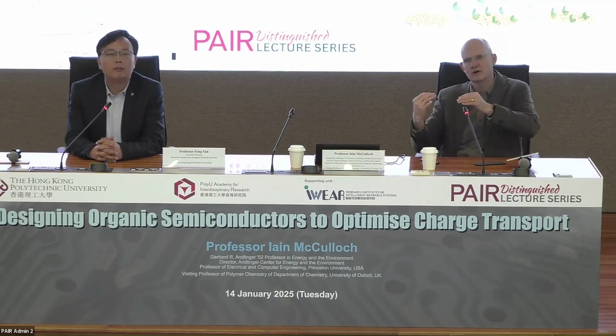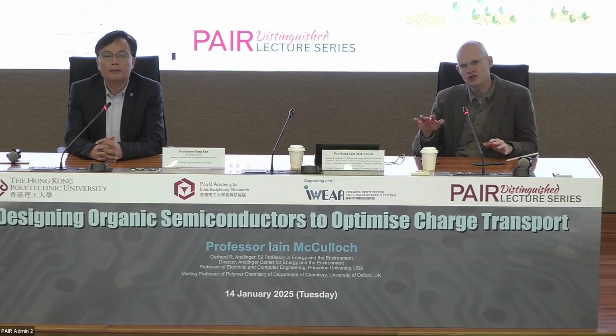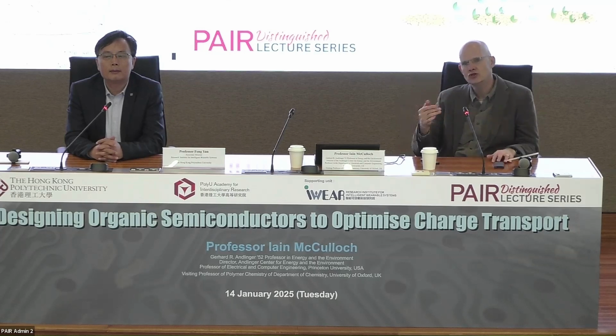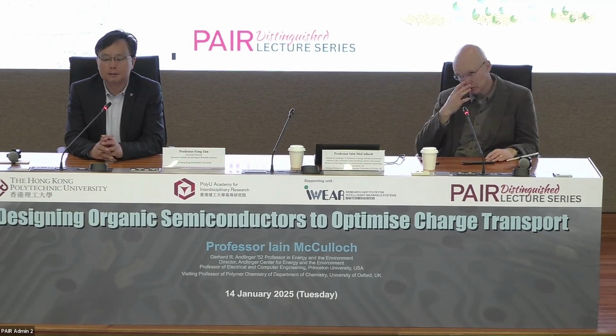And when something cross-links, the adhesion between layers decreases. The cohesion might increase in the layer, but because there's a slight densification, the layers lift up from each other a little bit, a very small amount. That's what they use that for anti-adhesive properties. And so that's an issue as well. So if you can avoid cross-linking, you should do so.